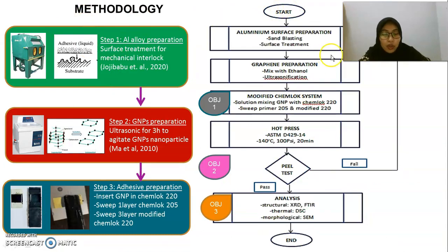This is my overview of the flow chart. Firstly, aluminum surface preparation uses sandblasting to roughen the surface, and this roughened surface allows mechanical interlock between the adhesive and the adherends. Next is step 2, GNP preparation by ultrasonic bath. This functions to agitate the GNP nanoparticles. Graphene is layered, layer by layer, but it will disperse if agitated at proper time and temperature.